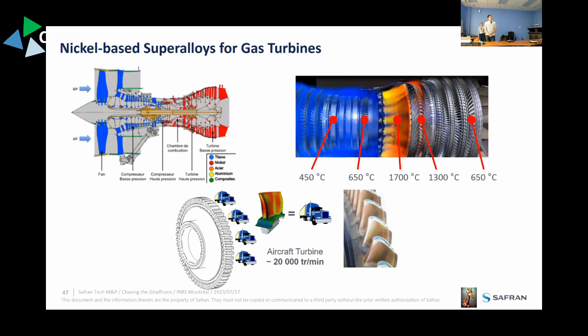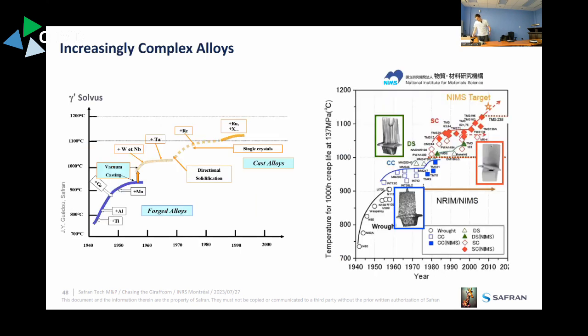So just as a quick primer on nickel-based superalloys, they're used a lot in gas turbines because they have excellent microstructural stability, environmental resistance, and mechanical resistance at high temperature, high enough that titanium alloys or steels cannot be used. So they are used either for the discs, but also for the blades. And blades are subjected to really high temperature and really high mechanical loads that make nickel-based alloys at the moment the most realistic option for these engines. And so this motivates the development of novel alloys.